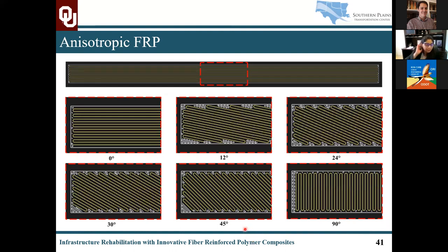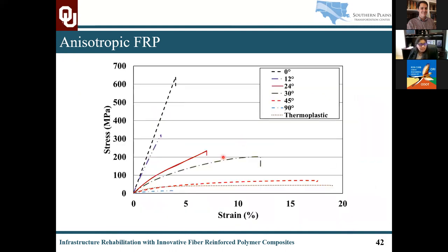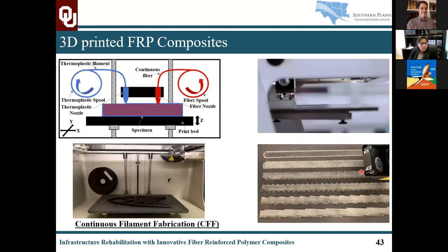The way that this particular implementation was adopted is using this anisotropic FRP. Now, FRP has different properties that can be observed in different fiber directions. So starting from 0, which offers that high strength, high stiffness material property, we transition slowly into different kinds of angles, which in turn reduce the capacity and stiffness, but improve the strain and non-linearity of these FRP. So if we see this transformation from a high strength to a low strength, we see that non-linearity being increased with every fiber orientation. And this particular aspect is used in this new innovative FRP composite system with 3D printing.